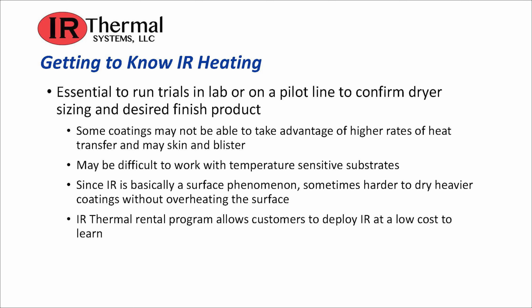If you're not familiar with IR heating, it's essential to run trials in a lab or on a pilot line to confirm dryer sizing and the desired finished product. We found some coatings may not be able to take advantage of the higher rates of heat transfer and may skin and blister, or may be difficult to work with on temperature-sensitive substrates. And since infrared is basically a surface phenomenon, sometimes it's harder to dry heavier coatings without overheating the surface. We have a rental program that allows customers to deploy infrared at a low cost to learn. It's one of the things that will help a lot of our customers.